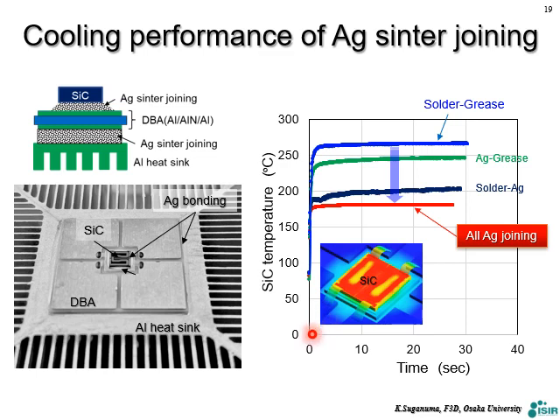So this is showing the silicon carbide top temperature change as a function of time. We put the same power onto the silicon carbide. Then look at the blue line. It increases immediately, in 2 or 3 seconds. It reaches 270 degrees C, a very high temperature. We have to think about this one. So this is solder conventional bonding or TIM materials, solder, grease. Then please compare this line with this one.